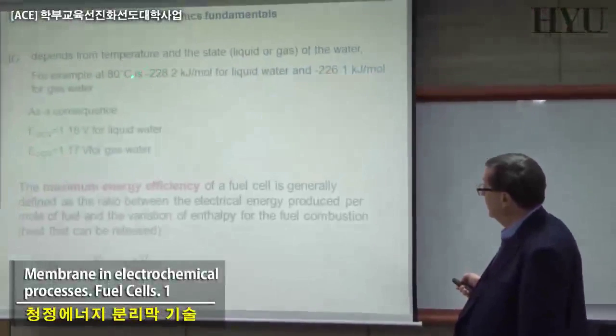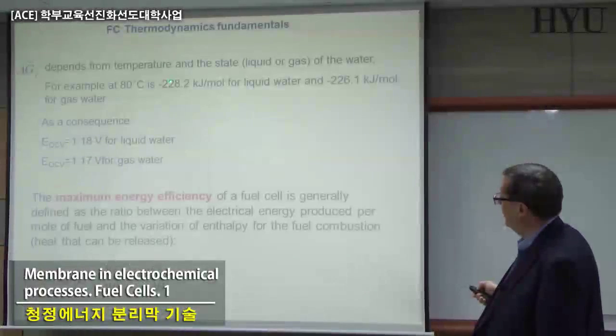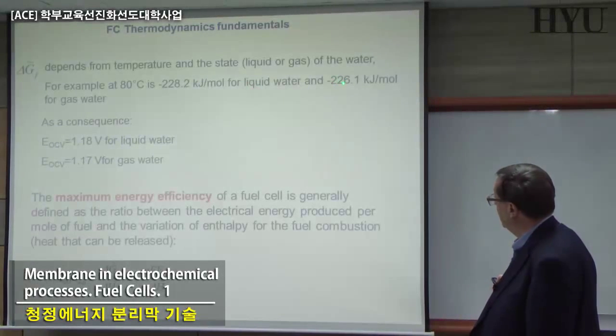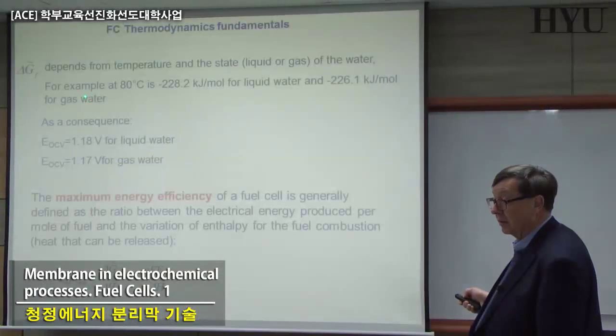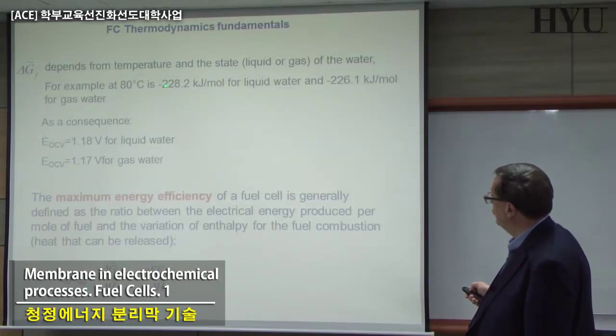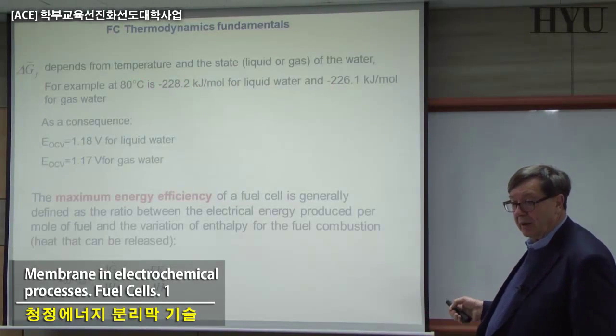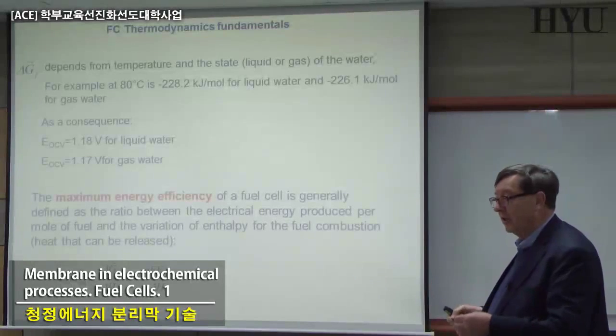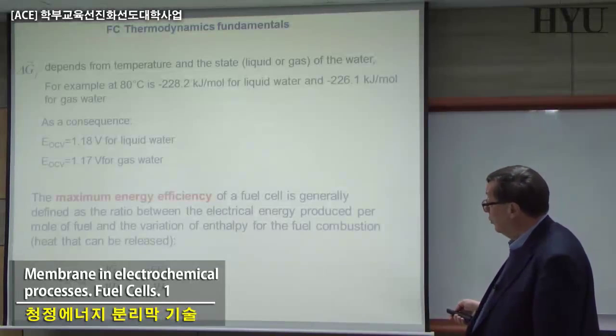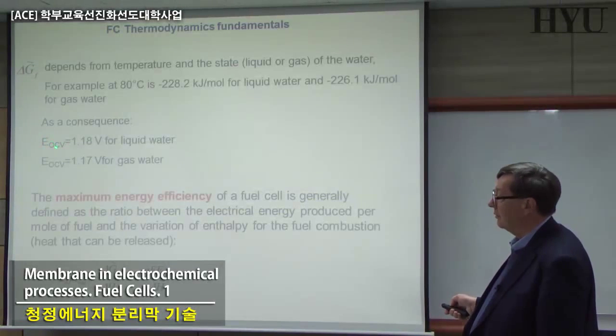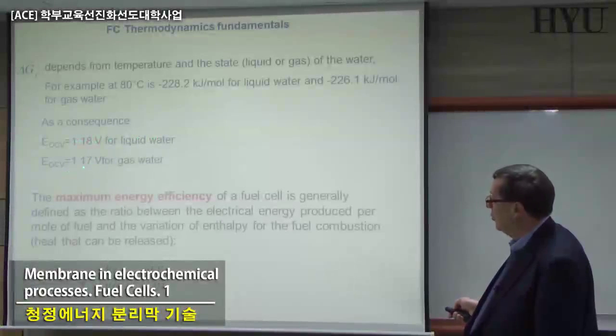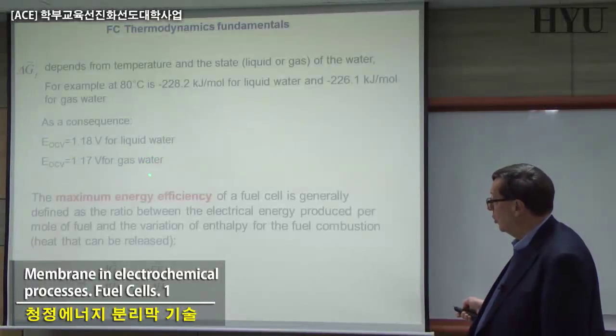At 80 degrees, this delta G is minus 228 kilojoule per mole for liquid, and 226 kilojoule per mole for gas. So it's not a huge difference, but it's a difference, and if you want to make your calculation, you have to remember about this. That's why you can define this voltage, which is 1.18 for liquid water, 1.17 for gas water.